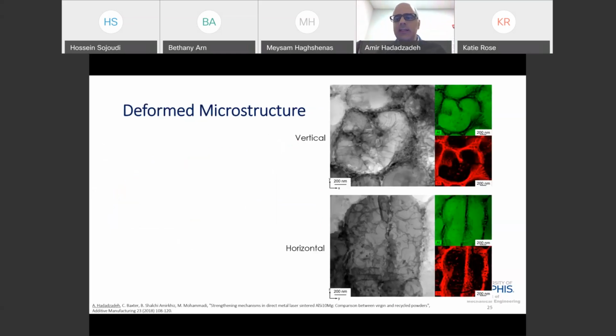So I started to look at the structure after the deformation. In both cases, again, here we see the STEM images, the TEM images in the scanning mode, along with the EDS maps, in this case, aluminum and silicon. So the density of dislocations has increased. And this is normal because during plastic deformation, we have motion of dislocations and generation of new dislocations. This is very basic in metallic materials.